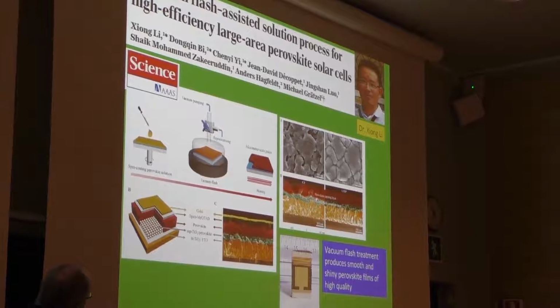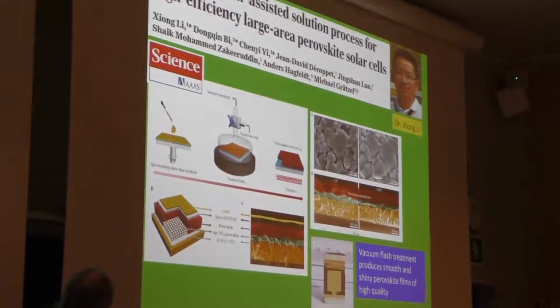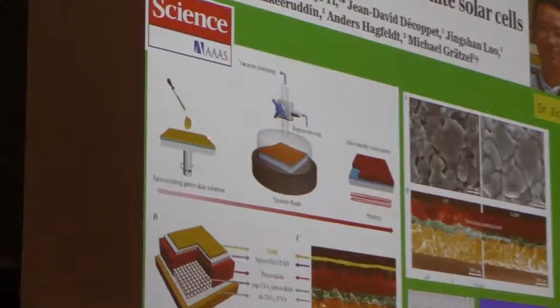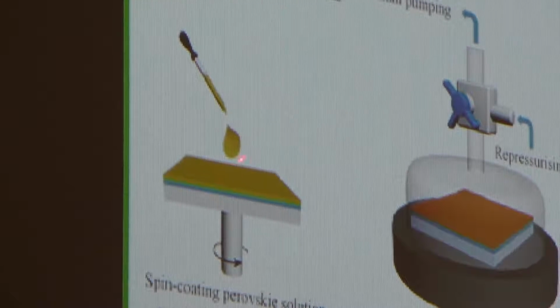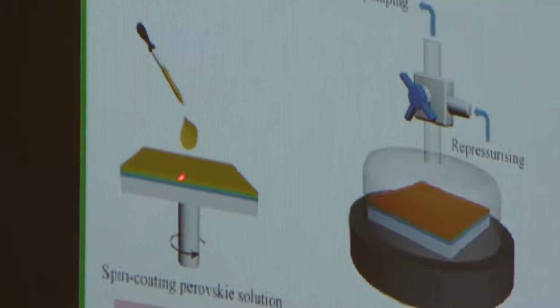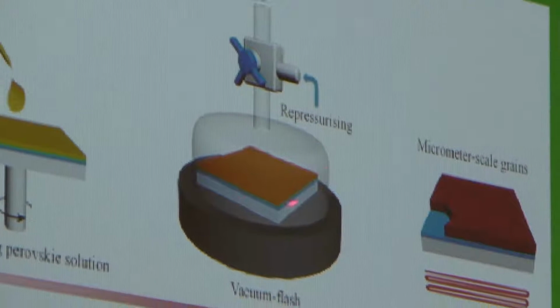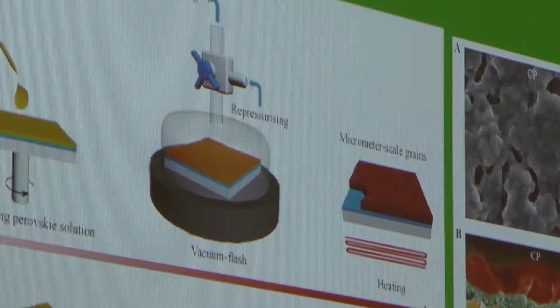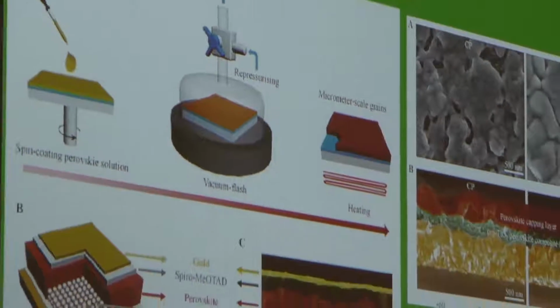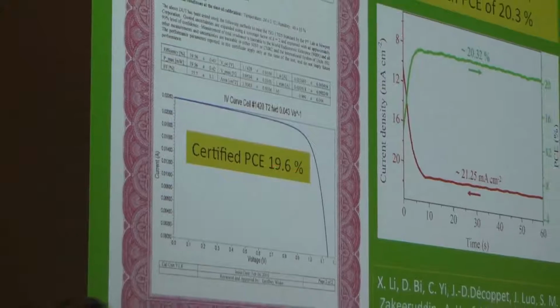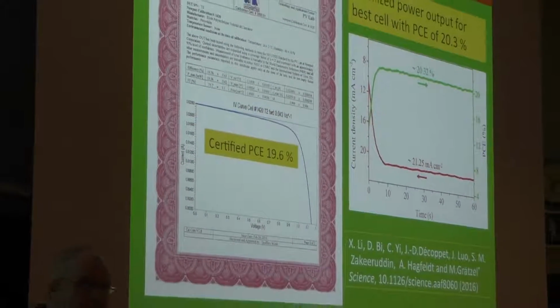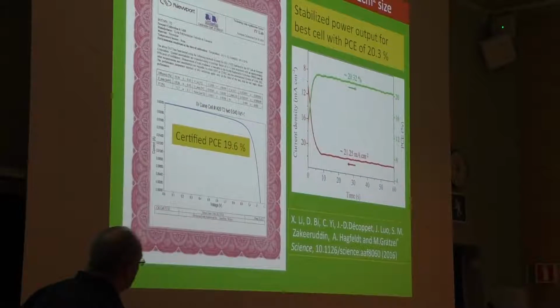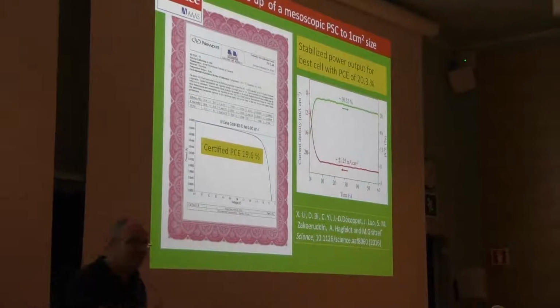What we did there: when you spin coat the perovskite solution, perovskite starts to form, and what people normally do is add what we call an anti-solvent. You reach supersaturation of the perovskite and you form a higher quality film, shiny, smooth and so on. We replaced this anti-solvent with a short and quick vacuum flash instead, so we can do larger areas. That was published in Science early this year. And we could then obtain a new world record of 19.6% for a 1 square centimeter cell. Then we were happy again, of course, but only for a week, because then Professor Zhou had 19.7%, so that's where it is today.